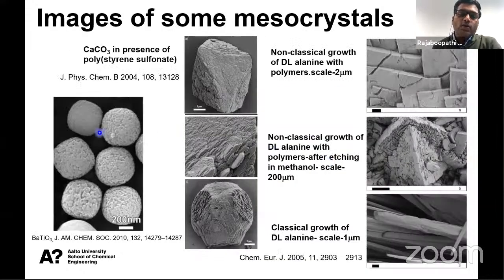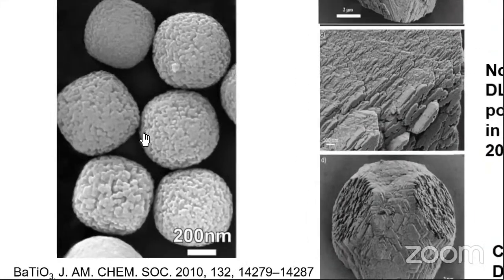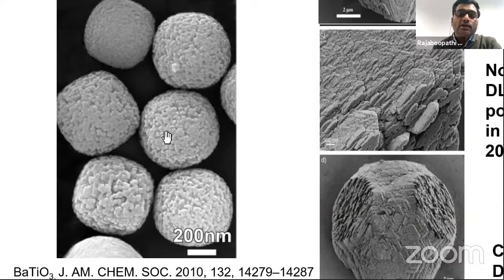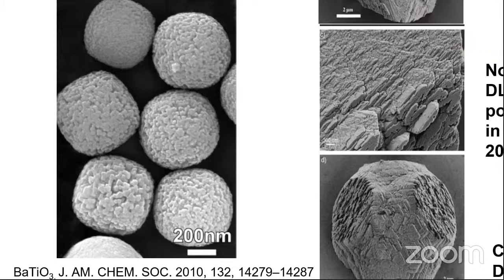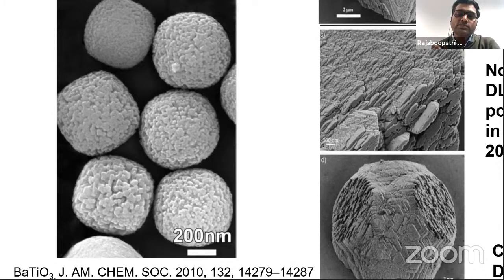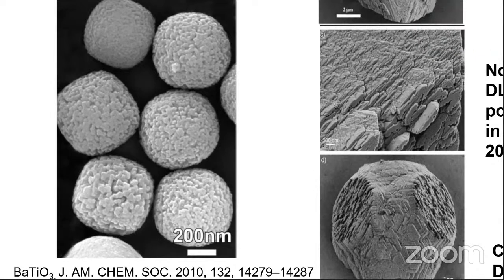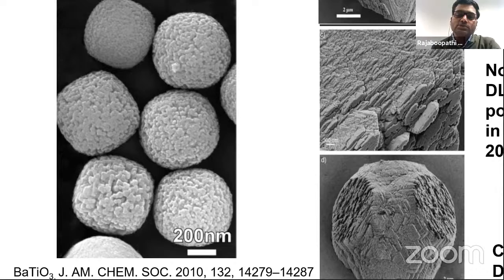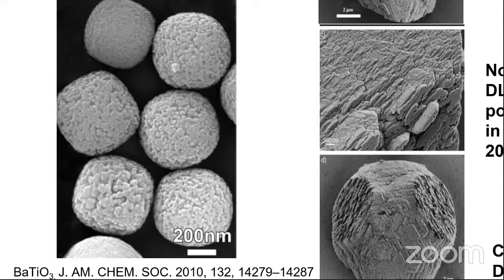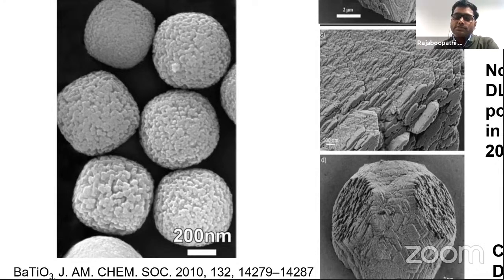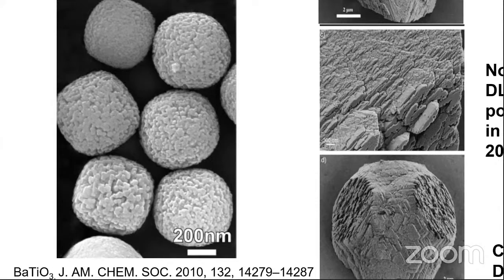And these are some laboratory grown mesocrystals. For example, this is a barium titanate where you can see clearly the particle attachment. The nanoparticles are attached together. Sometimes people report, for example in this paper, a superstructure. They didn't use the word mesocrystal, but they reported it as a superstructure because people are not so aware of what non-classical crystallization is, what mesocrystals are. Once they get a hierarchical structure, they use it for different applications. So actually this is mesocrystals.